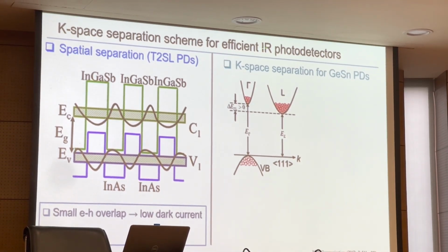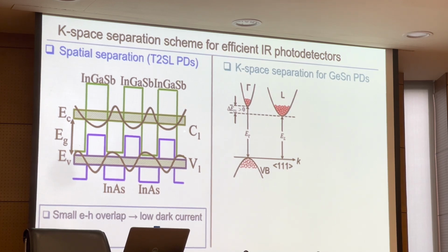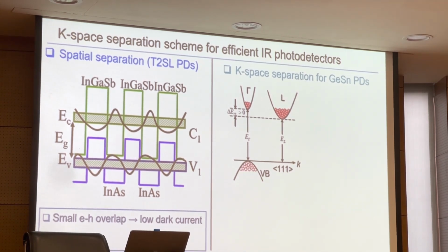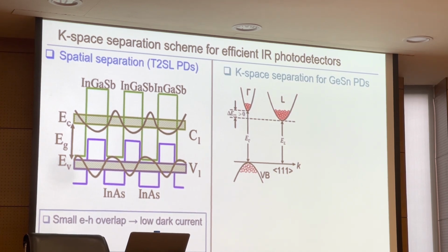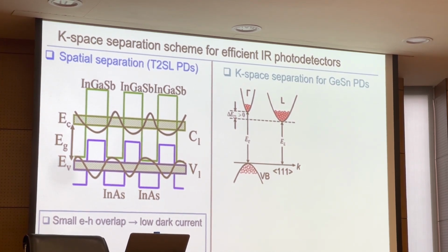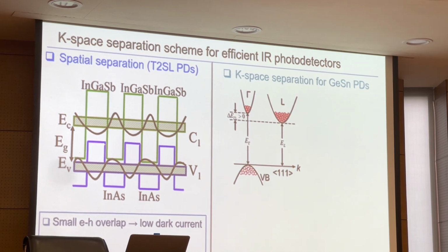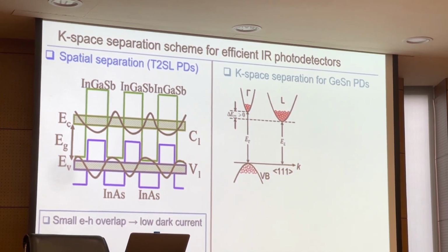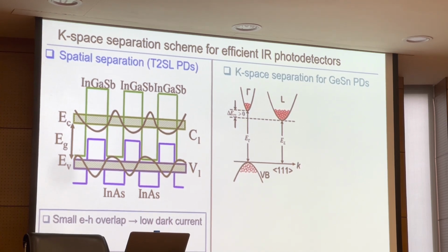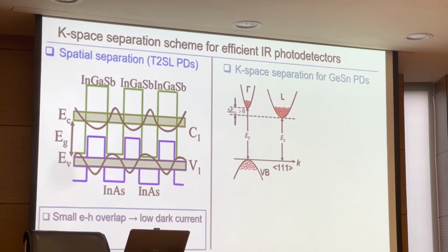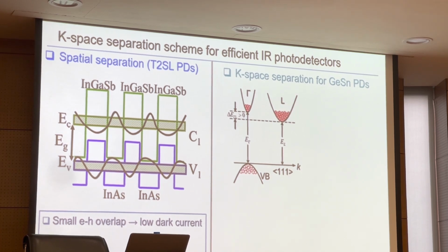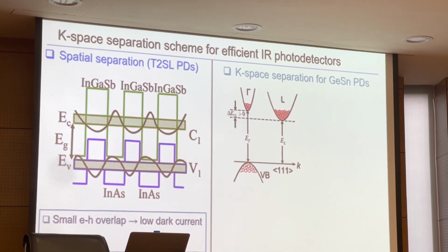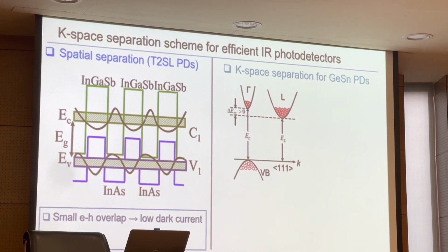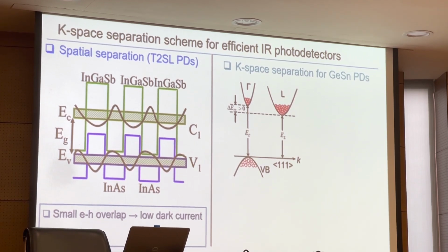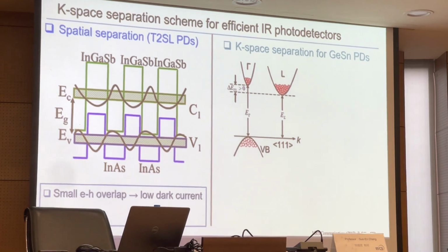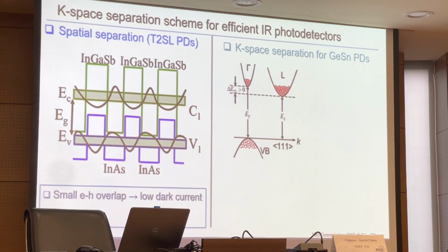We call it a type 2 superlattice. The idea for this structure is that the dark current can be very low because it is a type 2 band alignment—the conduction band minimum and valence band maximum are located at different positions. So the electron-hole wave function overlap is very small without any bias, and when you increase the bias, the electron-hole wave function overlap can increase, giving a very small dark current.